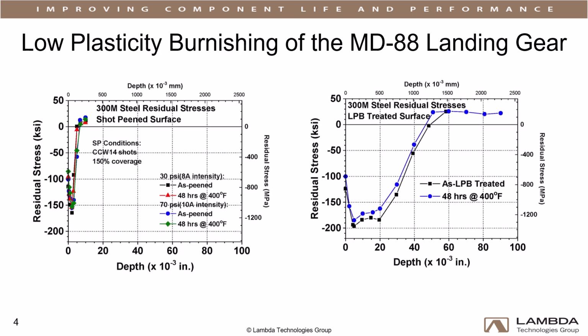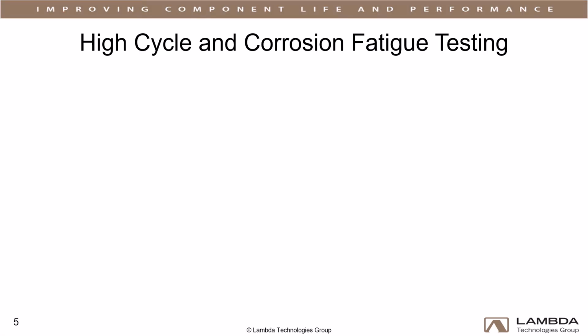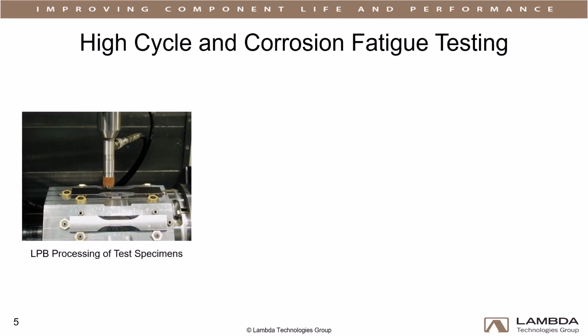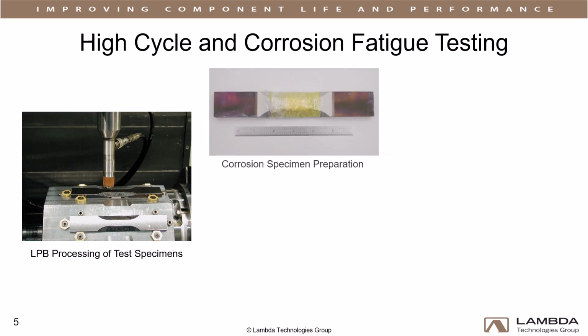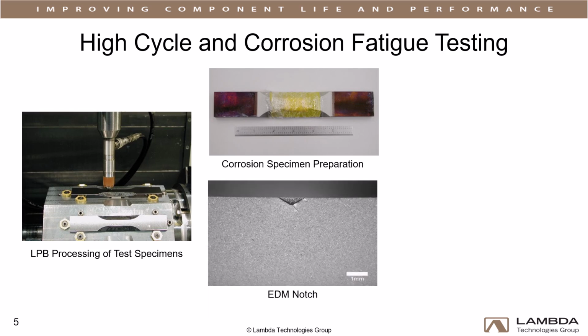For initial testing, LPB was compared to shot-peened and as-machined conditions using 4-point bending fatigue specimens and C-ring specimens machined from the 300M landing gear itself. LPB treatment produced a significantly greater magnitude of compression at 10 times the depth of the shot-peened specimens. The high cycle fatigue and corrosion fatigue performance of LPB-treated 300M steel was compared against shot-peened and baseline conditions. Corrosion specimens were prepared by wrapping tissue soaked in 3.5% salt solution around the gauge section. Damage was simulated with a semi-elliptical 0.5 mm EDM notch.